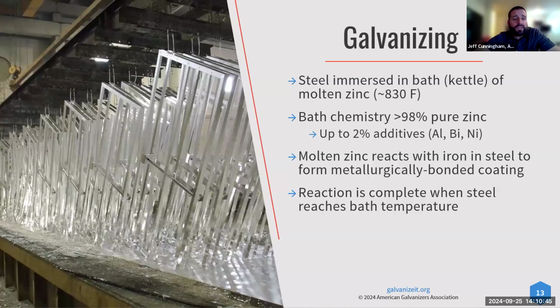Then the molten zinc reacts with the iron to form a metallurgically bonded coating. You're going to hear me say that a few times today, but it's actually fused together. It's not a mechanical bond where it's just kind of sitting on top. They're fused together, which we'll show you in a couple of slides. And then the reaction is complete when the steel reaches the bath temperature. Depending on how big the piece is, it could be as little as 2 minutes up to 12, 15 minutes.